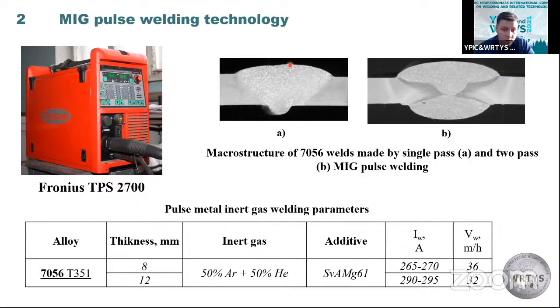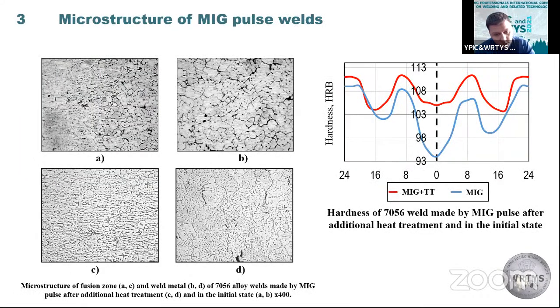We tried to weld it in two passes. We used MIG pulse welding in an inert gas, with 50% argon and 50% helium. It was welded in our institute. The microstructure was partly good, but there was very high softening in the middle of the area. A better microstructure, as you can see, this was before, as welded joints, and this is after heat treatment.